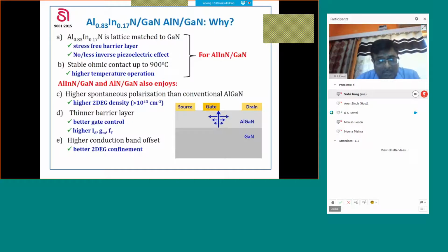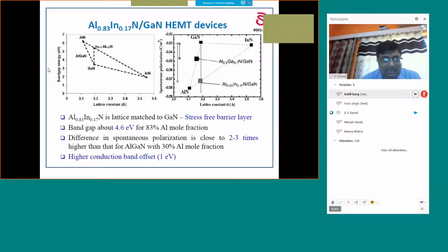So this aluminium indium nitride barrier layer over gallium nitride is giving us two advantages. One is thin layers, important for very high frequency devices, and second is it is lattice matched, so there is no piezoelectric effect, so no mechanical stress and fewer defects, so a more reliable device. You can see that indium aluminium nitride at 17% is lattice matched to gallium nitride.